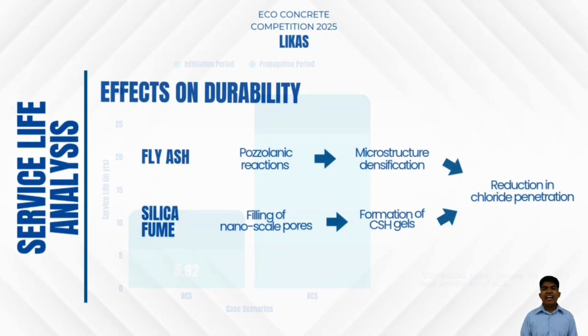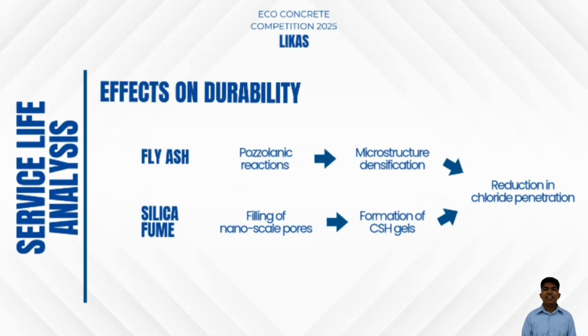The secret? Fly ash and silica fume team up to block chloride invasion. Fly ash acts like a concrete densifier. Its pozzolanic reactions plug pores and slow down chloride movement. Silica fume fills the microscopic gaps that even fly ash cannot reach, forming extra CSH gels to seal the microstructure.